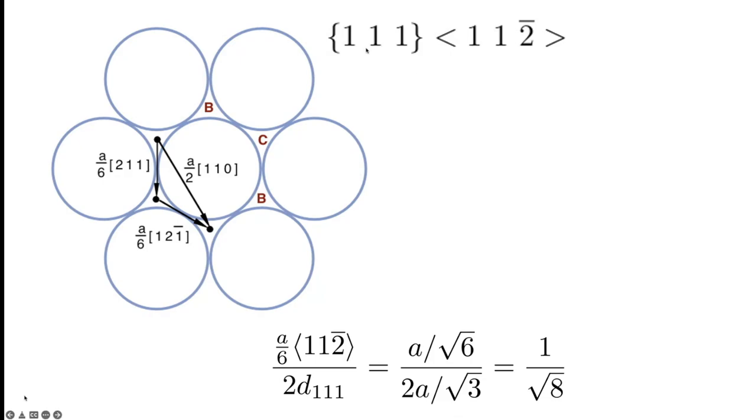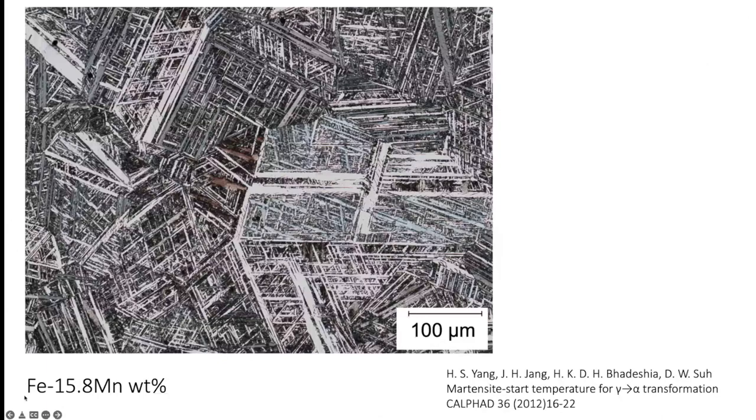And of course, the martensite will form with a habit plane which is exactly 1-1-1. It's not irrational because the shear deformation is what changes the austenite into hexagonal structure. You don't need any other complication. It's a simple shear, okay? And that's why when you look at the structure, it looks extremely beautiful, because in any given austenite grain, you have only four 1-1-1 type planes.